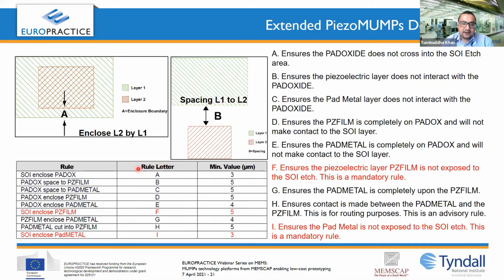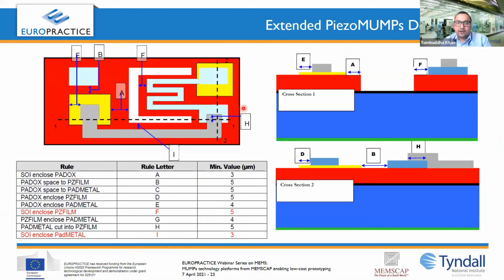For them, there are certain rule letters that have been defined. So SOI encloses pad oxide. The reason for it is given here. SOI encloses the pad oxide by 3 micron. That means it ensures that the pad oxide doesn't cross into the SOI Etch area. If I go here, you see the edge of the pad oxide will be 3 micron away from the edge of the silicon layer. Similarly, there are a few more rule letters given, and their corresponding values are also given here. But you can see that two of them are in red, that is F and I. They are mandatory to be followed, and the rest are recommended rules that are to be followed by the designer.